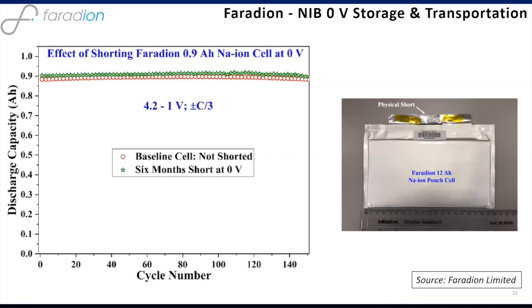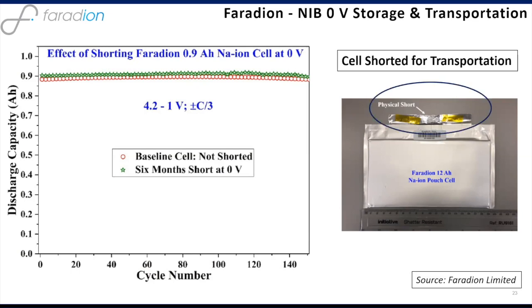Really important for us, and I think a differentiator over any graphite-based lithium-ion cell, is that we can store and transport our cells at zero volts. I said that at the start of the presentation. One of the advantages of having aluminium, aluminum current collectors on both sides of the cell is we can physically short the cells for storage and transportation with no detriment. There's no increase in impedance. There's no detriment in terms of cell performance. And right now, everything that we store and transport, for good safety reasons, is physically shorted across the terminals.